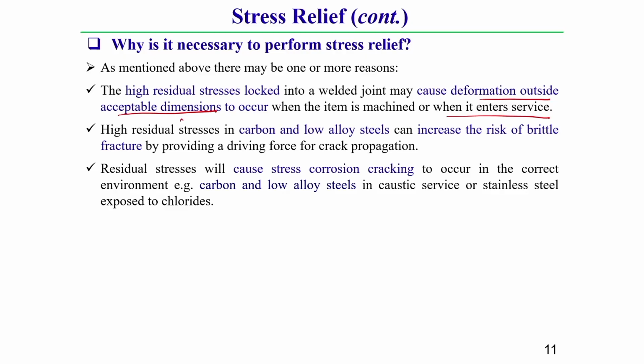Apart from this, if there is a high residual stress in a weld specimen of carbon or low alloy steel type, then it increases the risk of brittle fracture. So, if we do this stress relief operation, then we can eliminate this risk of brittle fracture. Apart from this, if we remove this tensile residual stress, it also reduces the cause of stress corrosion cracking. This is another phenomenon you should keep in mind.